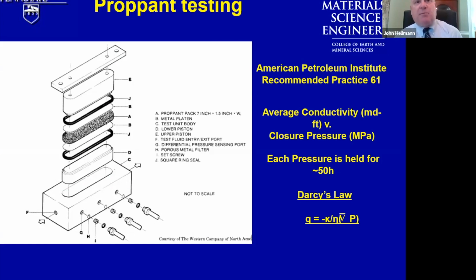Liquid and gas permeability is measured using an American Petroleum Institute 61 standard test that's now known as the ISO 13503-2 test, in which an assemblage of particles is constrained in a steel die and a uniaxial load is applied via platens. A liquid solution of KCl in water, potassium chloride in water, is passed through the particle bed, and pressure drops are measured using pressure transducers.